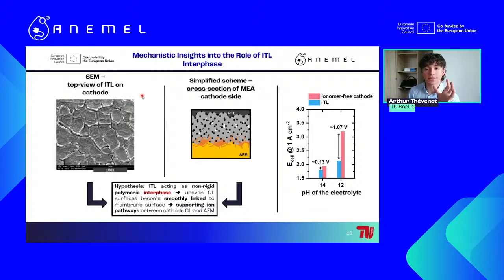Now, from these results, this brought us to this hypothesis that we have about the ionomer top layer: that it is acting as a non-rigid polymeric interface, and therefore the uneven catalyst layer surface will become smoothly linked to the membrane surface. And therefore this will be supporting the ion pathways between the cathode catalyst layer and your AEM membrane.